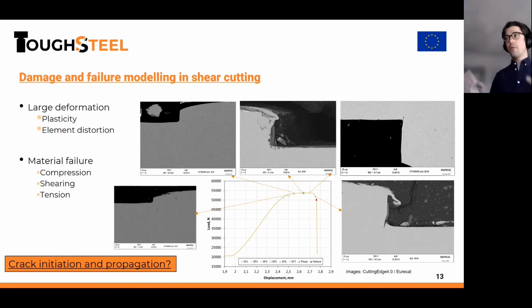But to be able to numerically model shear cutting, this puts high demands on your material models and your damage and failure models. And here you can see the shear cutting process and the cut edges in separate stages along the process. These images are from interrupted punching tests conducted by Eurecat, where the shear cutting process was paused at a number of stages along the process, and the cut edges were examined.